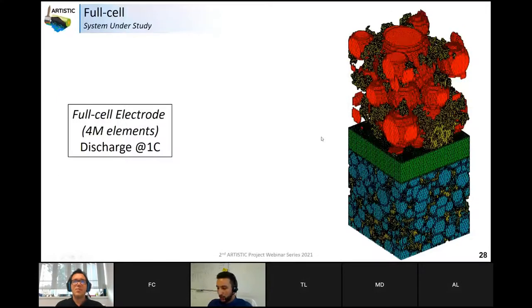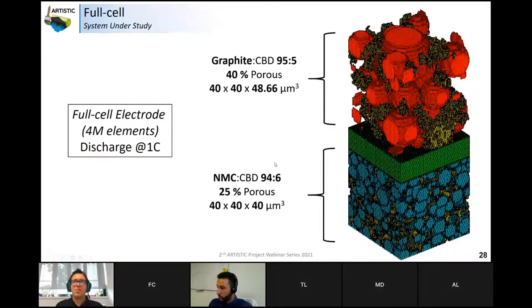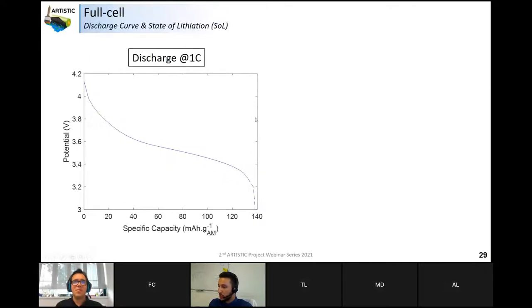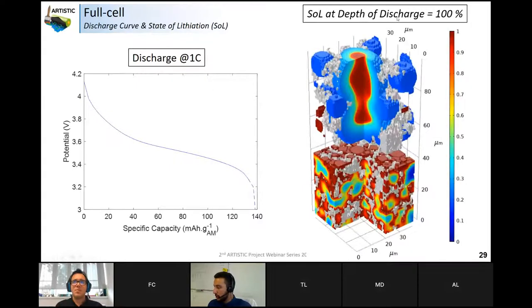And then really quickly, because of the time constraint, I will go through an example of a 3D full cell electrode discharged at 1C, just to show that this tool allows you really state-of-the-art and even more simulations. Here I just generated these two electrodes at 1C discharge, so you got 140 for NMC, so it's 140 milliampere hours per gram, which is kind of what you would expect at an experimental level. Here is the end of discharge profile of your state of lithiation. The more lithium you have inside, the more red it is. So you can see high gradients because of the big particles in graphite, whereas in NMC you have fewer gradients because their particles are smaller.